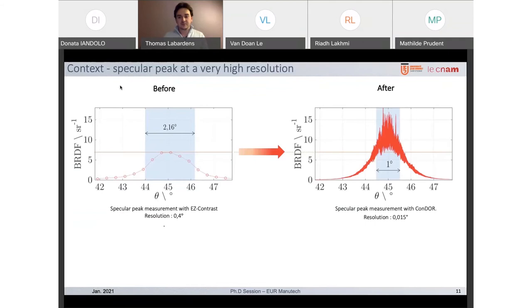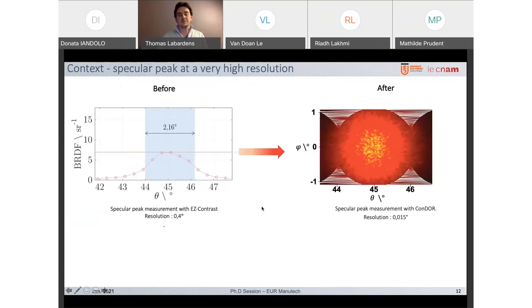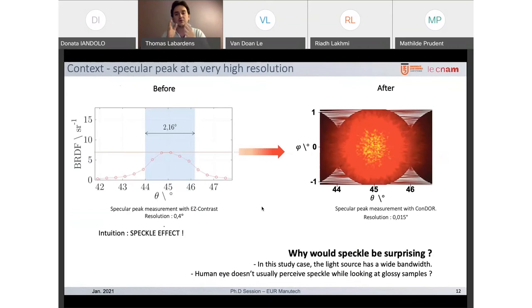But when we look at this peak from the top, here we have this image. Maybe we don't have any intuition when we see that, but as optical engineers, we watched this image and said, okay, maybe this is a speckle effect. I will introduce you to what a speckle effect is, but first, why would speckle be surprising in this particular case? Well, in this study case, we are using white light. The light source has a wide bandwidth, and speckle effect usually appears with lasers or with highly collimated lights. So it is surprising to have speckle within the specular peak.